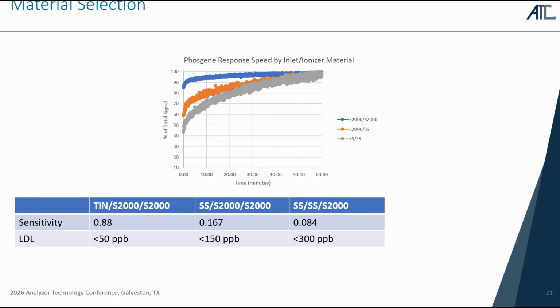So the first was ensuring that the material selection was correct for the application. So we have different common applications that you can use, such as bare stainless steel, coated stainless steel with an inert coating, something like a SilcoNert 2000. You can also move towards Dursan or titanium nitride for additional considerations for corrosivity and longevity of the system.